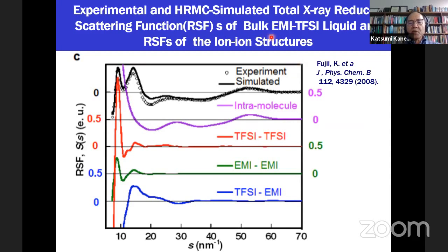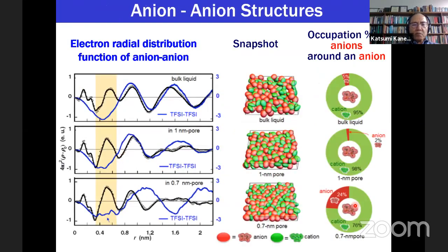Well, this is the bulk EMIM TFSI liquid case, compared with experiment and simulations. Then the TFSI anion-anion, anion-cation, and cation-cation radial distribution functions we compared. Here I will show you the anion-anion structure, because the anion has more electrons, and the larger electron number gives a more reliable X-ray scattering cross section.